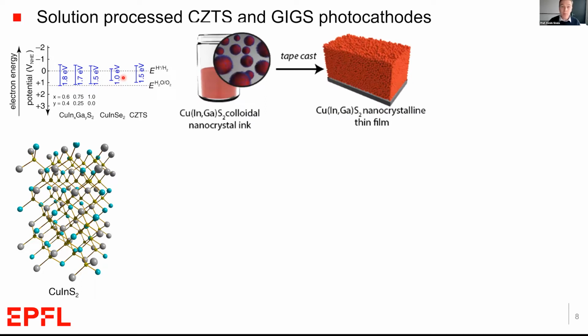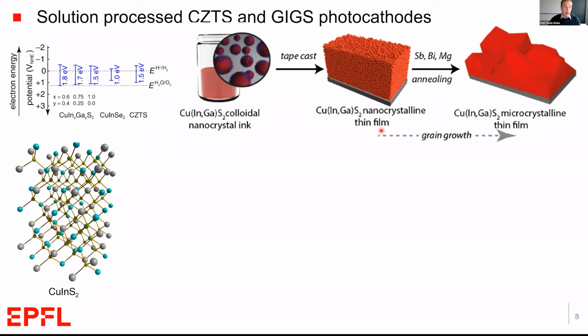We can also make nanoparticles of these materials by simple hot injection methods and coat them into electrodes. What we found to be very important is the need to anneal in a special way to reduce the grain boundaries in these electrodes and make the crystals grow from nanocrystals into microcrystals.